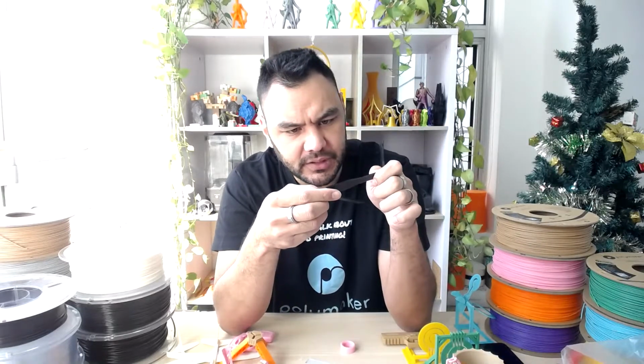So my guess here, like I explained, is that it broke as we predicted. And why it delaminated, I think is a similar reason as PCABS. Actually, PCPBT required an even hotter chamber, around 100 degrees, in order to make very strong layer adhesion. I'm pretty sure I can delaminate this very easily. Yeah, look at this. And this was because it was printed on the Ender 3. So most likely it was printed with 260 maximum, or even if it was printed on the Ultimaker. Let me check. Yeah, no, I don't think so. But even if it was printed on the Ultimaker at 280, it's still not enough for PCPBT. But very interesting how it behaved, how it broke.